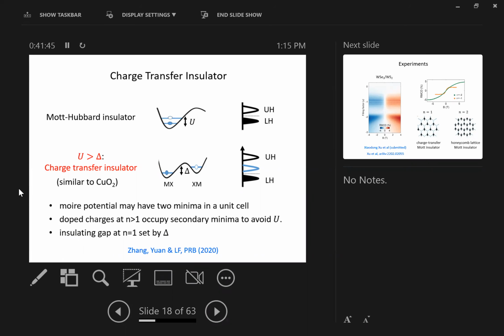So this is another kind of Moiré insulator that's called in the literature the charge transfer insulator. A classic example is actually the cuprates. In cuprates, those charges actually live on oxygen, even though the local moments in the insulating state come from copper. So if you look at the energy diagram, there's an upper and lower Hubbard band associated with the primary energy minimum that's separated by Hubbard U. The upper Hubbard band consists of doubly occupied sites. The lower Hubbard band is formed by holes. But then inside this big gap, there are low-lying states, the so-called charge transfer band. These come from the secondary potential minimum, a second sublattice.